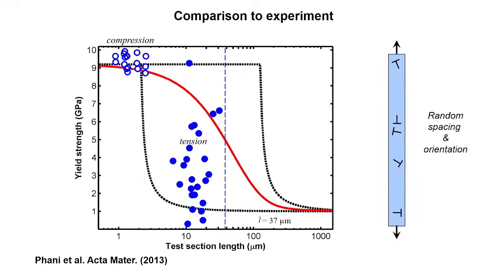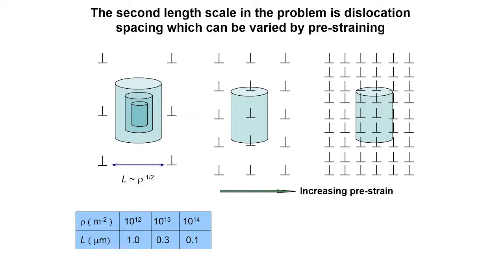So in addition to these two other length scales, where you change the size of the specimen, making them smaller or larger, you can also change the spacing between dislocations. So this is well annealed crystal. This is crystal that has some cold work in it, and this is crystal that has a lot of cold work in it. And what you would find is that as you take the same specimen size, you would sample more and more dislocations as you had more and more defects in them. And this is what you would expect: when you go from theoretical to bulk, with increasing dislocation density, you would expect that curve to shift to the left. And that's in fact what we see.